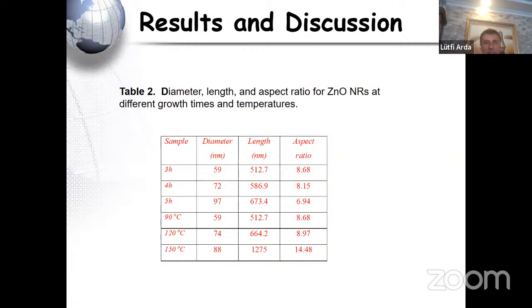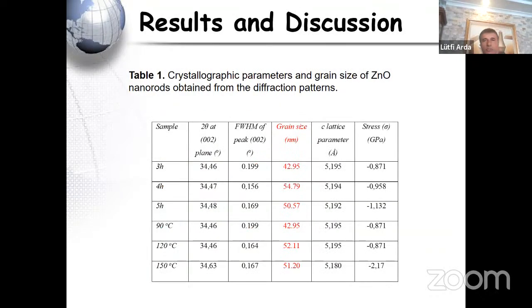And this table is diameter, length, and aspect ratio for the zinc oxide nanorods for the 3 growth times and the 3 different temperatures. Okay, let's turn again to table 1. From table 1, look at the C lattice parameter. It decreased from 5.195 to 5.192 angstrom as growth time increased from 3 hours to 5 hours, confirming a slight reduction in C values with increasing growth time.